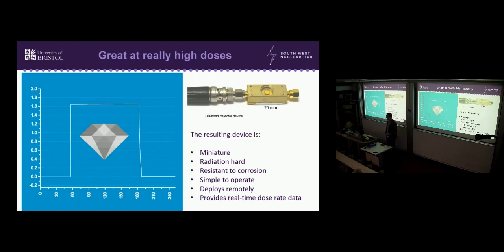Very simple to operate because it's operated by big, hairy, gorilla-type men at Sellafield's site without breaking it. Our first prototypes on site got broken all the time, actually. And it gives you real-time dose rate data, which is the first time they've ever had a technology which can do that, which means you can get dose as a function of time and position, which means that they can actually characterize their facilities in a way they could never before.